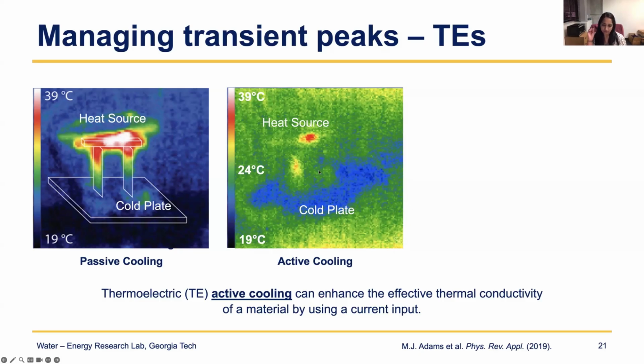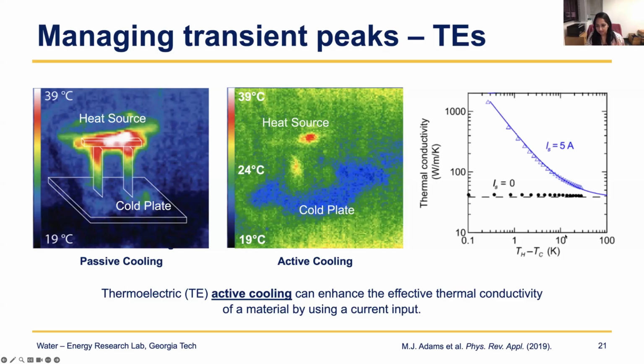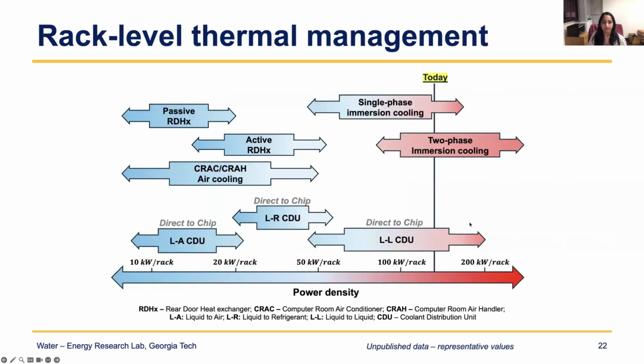So this again is a way in which you can just source a current, very quickly dissipate a hot spot using a thermoelectric metal. So this is based on iron and nickel alloys rather than traditional bismuth telluride. And essentially what it's doing is it's increasing the effective thermal conductivity of the thermoelectric material. So this is something else that we've been working on. At the rack level also, we look at the different cooling technologies. So again, moving from traditional air-cooled heat exchangers and components to a lot of direct-to-chip, so liquid cooling.